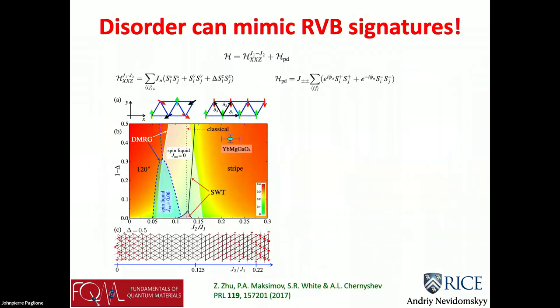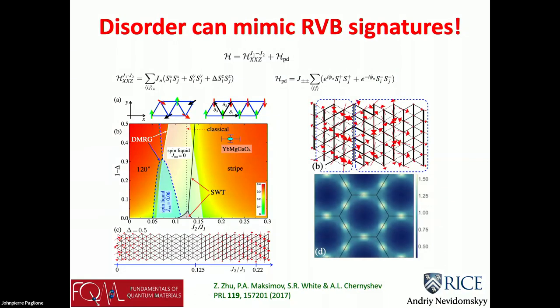Unfortunately, disorder again becomes a problem. And in fact, it was shown that if you just take the same system and you disorder it, this is a theoretical calculation showing that you could actually get a pattern that resembles very much what you see in the diffuse neutron scattering. And so Sasha Chernyshev called this a quantum mimicry, where disorder can mimic the smoking gun. So in other words, it's not such a smoking gun if there is a way to fake it.